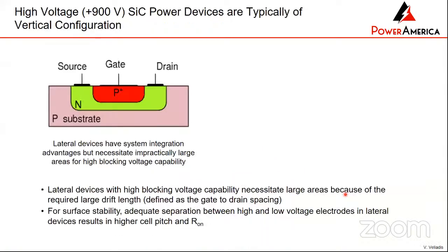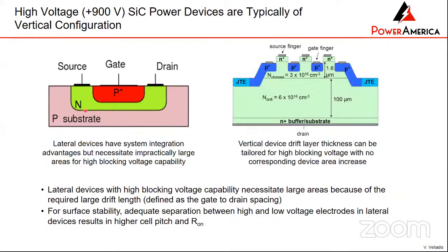So devices in silicon carbide, and in general power devices, can be made lateral or they can be made vertical. If you make a lateral device and you want high voltage, the higher the voltage, the bigger the separation between the gate of the device and the drain of the device. So when you get to a certain level, which is about 900 volts, this separation becomes so big that if your device on the wafer is lateral, it's taking too much space on the wafer.